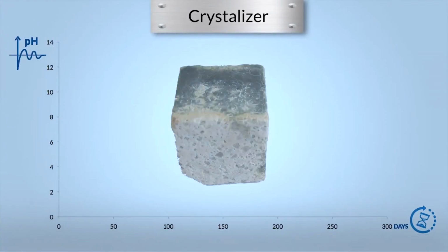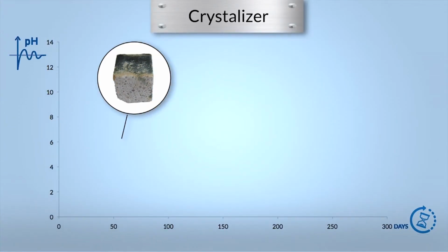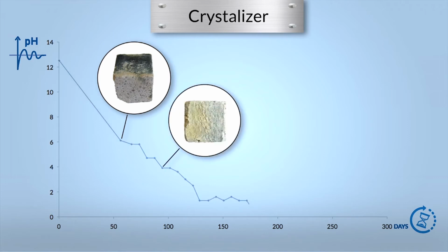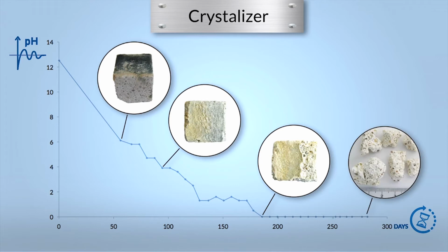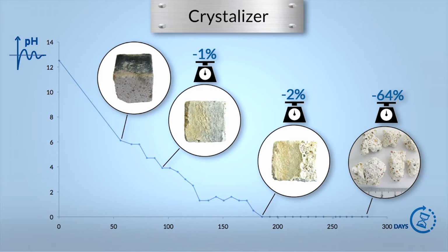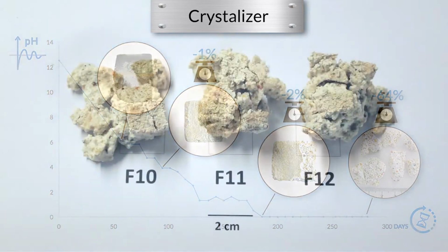A similar behavior is observed with mortar specimens made with a crystallization admixture claimed to protect the concrete sewers from H2S corrosion by sealing the porosity. Cubes are severely damaged within a few months. The pH lowers to 0, and the weight loss after 9 months is 64%.